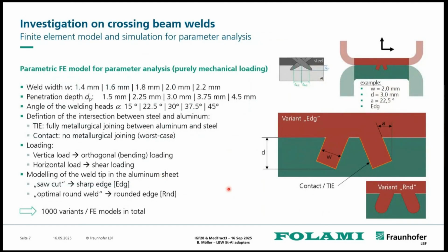Therefore, we started with an initial investigation of how such a crossing beam weld could look in terms of local welding and geometry parameters. So how should this joining of steel material work? The upper part should be made of steel, as you can see here, and the lower one, in this case the green one, would be the aluminum. We are mainly welding from the top with two crossing beams into the material, and then we get some kind of geometry between steel and aluminum material, which could have such an edge shape or more a round shape.